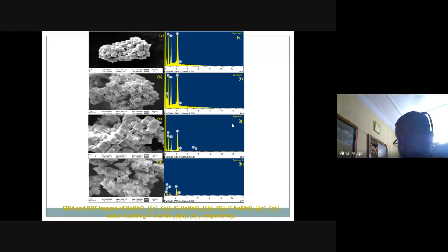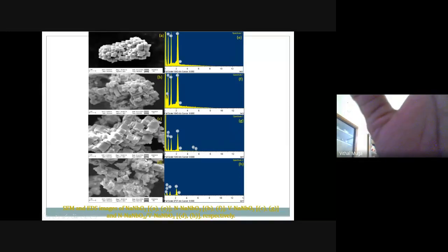Now this picture shows the FESEM of the first one, NaNbO3, parent material, N doped material, V doped material, and the last one is the ground, physically mixed N doped NaNbO3 and V doped NaNbO3. Now this is where actually my student has scored points with reference to the adjudicator. Now you look at all these things, the edges are fine. So that means what? The material is intact. But you look at this picture, the edges have become actually broken.